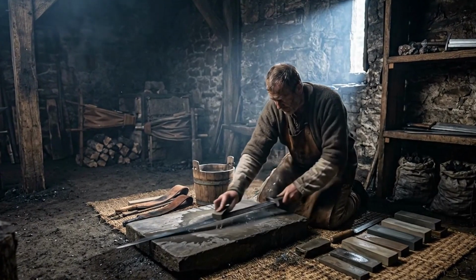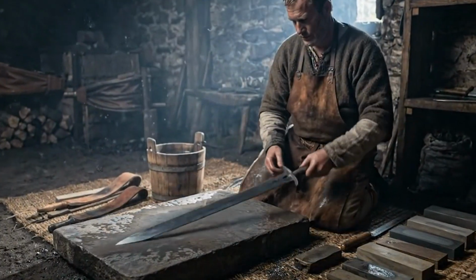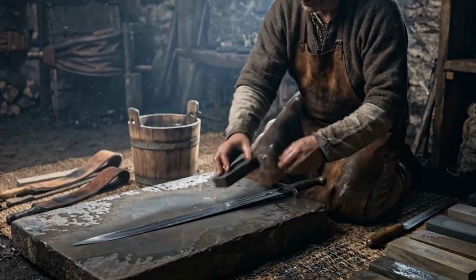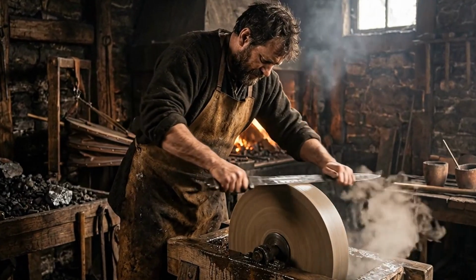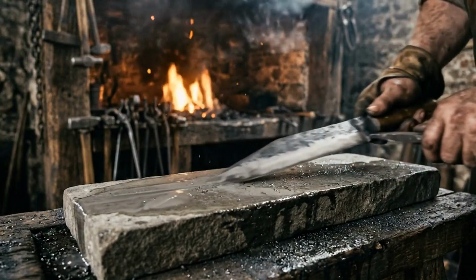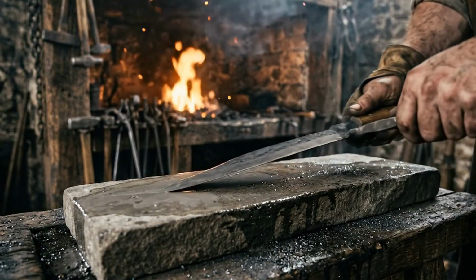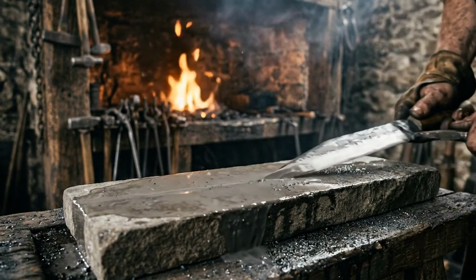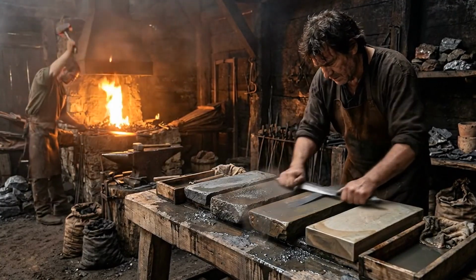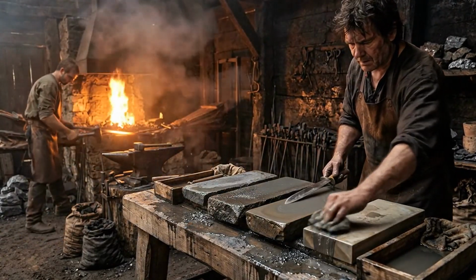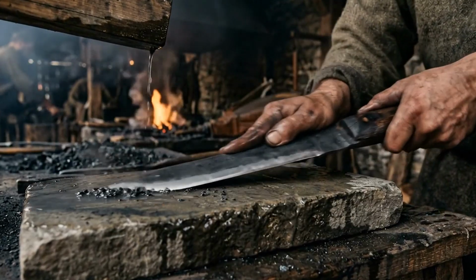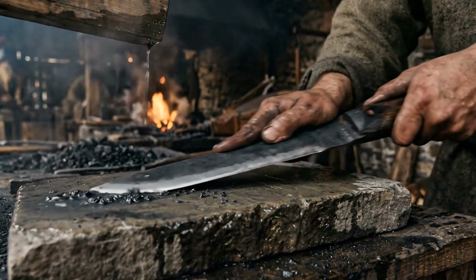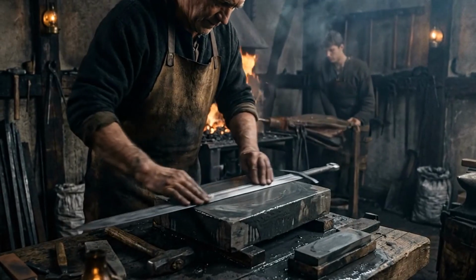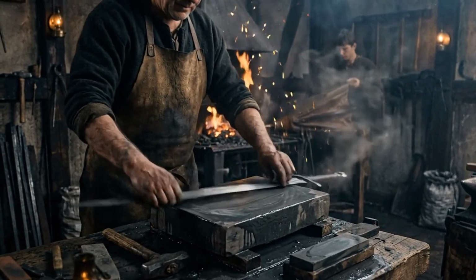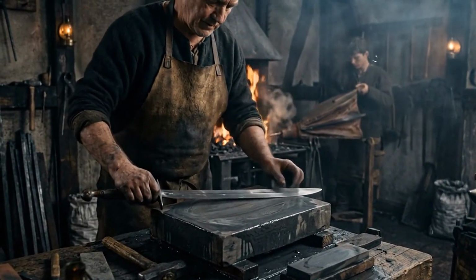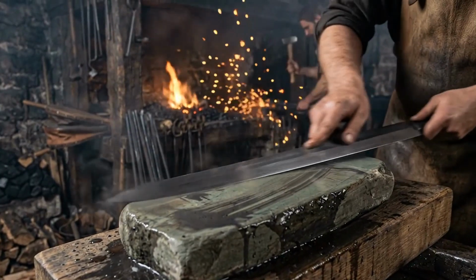The blade was then passed to the polisher, the togishi, whose work was entirely separate from the smith's and required its own years of training. The polishing process, the togi, proceeded through a sequence of progressively finer abrasive stones, beginning with coarse stones that removed the rough surface left by the forge and established the final geometry of the blade's bevels and faces. Intermediate stones refined the surface further, removing the scratches left by each previous stone and revealing the steel's underlying grain.